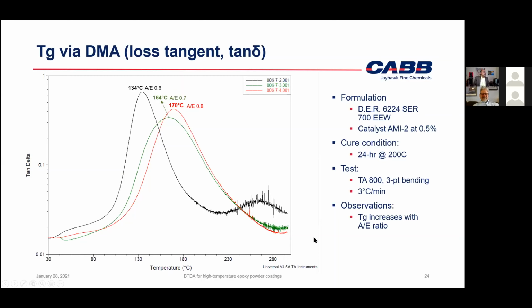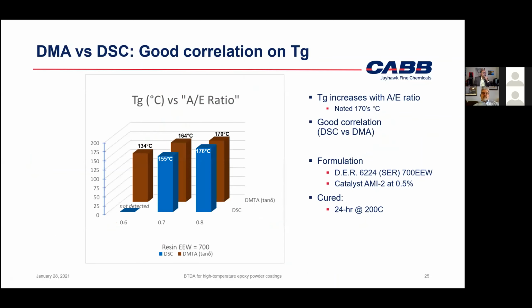Sorry. We'll get moving. So just to show you, we didn't have a chance to do DMA testing on all the specimens, but Nicola Billick really did some great work preparing specimens from the powders that we had. And here's a series of the same resin that we've been seeing, the 700 equivalent resin. If you have the A/E ratio of 0.6, 0.7, and 0.8, your Tg starts going up from 134C to 164 and 170. And I think you recognize that some of these Tgs we couldn't detect by DSC. So it is nice to actually see that you can get 170 Celsius Tg. And we did have confirmation of that particular data from DSC actually.